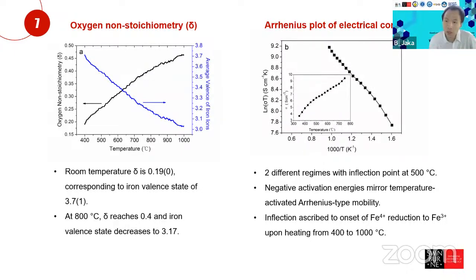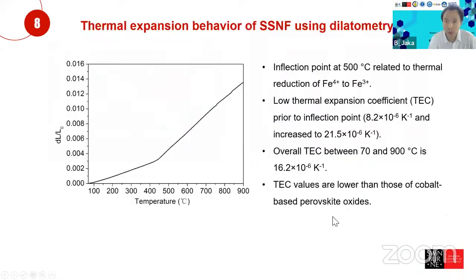And the electronic conductivity, generally in perovskite that contains a transition metal ion, is much higher than the oxygen ionic conductivity. So we can safely say that the electrical conductivity in perovskite reflects the electronic conductivity of a perovskite. So we have two different regimes with an inflection point at 500 degrees Celsius. And the inflection is ascribed to the reduction of Fe4+ to Fe3+ when we heat it from 400 to 1000 degrees Celsius.